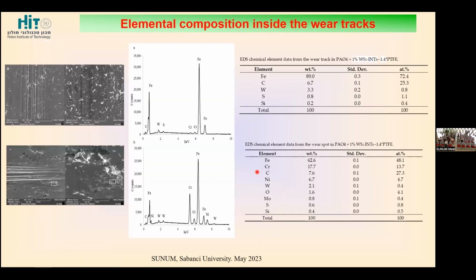We also measured the elemental composition in the nanoparticles before and after friction, and inside the wear tracks. This composition again proved that with the best coating, the properties are also the best. They are stable, they reduce friction, and they are stable under heating, so even at very high temperatures, 400, 500 degrees, we still have high stability.